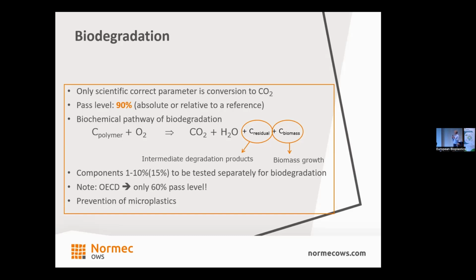Still, there is an additional requirement in many standards, not yet in the European one, that components in a material between 1 and 10%, or even in ISO level between 1 and 15%, have to be tested separately for biodegradation. This means that you cannot make any starch-based material anymore with 8% polyethylene. That will not pass this testing. Still possible in effect in Europe, but it should be changed and will be changed.